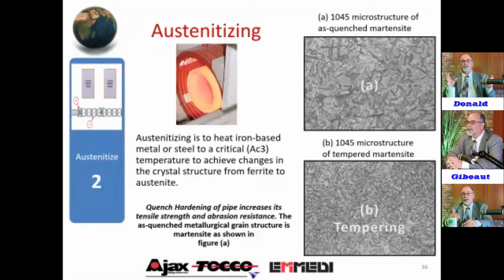Again, in the austenitizer, we're looking at an as-quench martensite grain structure to the right, and the uniformity coming out of our quench is 95 plus on the uniformity of that grain. And typically we get within 1 or 2 points on the Rockwell scale uniformity. The quench is the major component here. And I'll show you on the TTT curve, the AC3 line.